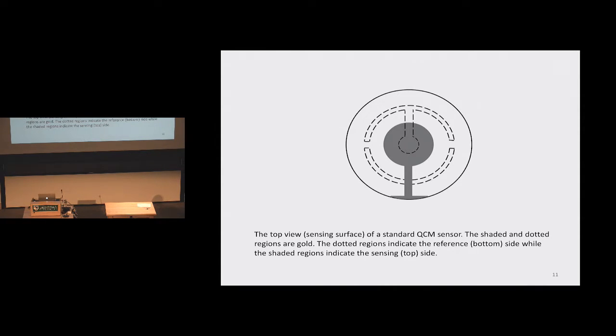This particular QCM is a standard device that's used in thin film deposition systems, where you're depositing a thin film onto a substrate, and that thin film on that substrate corresponds to a particular device for which the thin film's thickness is an important parameter. So what you do is you have this particular device in concert with the actual device that you're doing, and the frequency of this device changes, and as the frequency of this device changes, it's indicative of how much mass is onto that device. And if you know the density of the material you're depositing, then you'll know the thickness of what that film is, and that's a critical parameter in the deposition system.